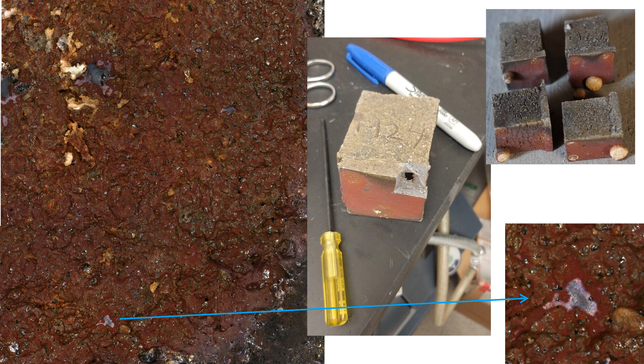Those of you who fire for reduction cool reds will be familiar with the tendency to find them mainly on surfaces that have been exposed to the kiln atmosphere, but not covered over with fly ash — for example, on the backsides or bottoms of pots. The microscope image shows a magnified view of something like one square centimeter of reduction cool red surface. Already at this magnification, we can see that the color is quite splotchy, varying from purple to intense red, and that there are what look like tiny black crystals all over the place. This clay body is Dan Murphy's 50-50 mix of Lizella and Fredericksburg fire clay.